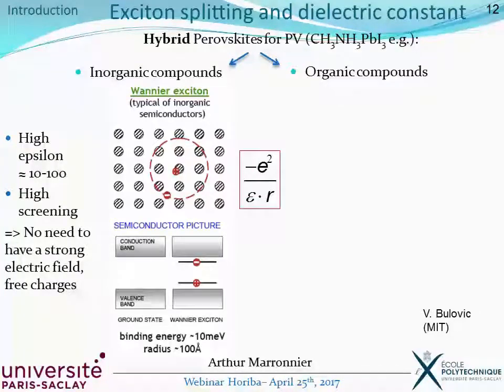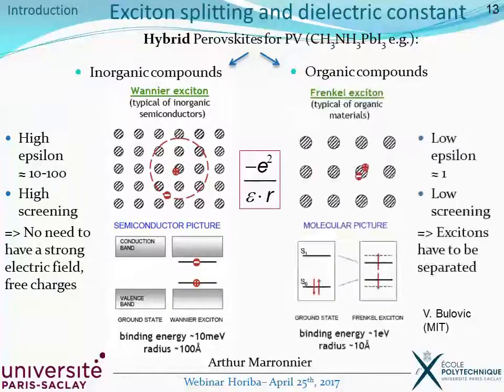And this is good news in general for photovoltaics, because it means that you don't need a strong electric field in order to extract your free carriers. And it's quite the opposite for organic compounds. They have Frenkel excitons, very tightly bound excitons, which are associated with a low value for epsilon, the dielectric constant, which is in general bad news for solar cells. You need a strong field in order to separate those excitons. So one of the first questions in my PhD was to understand where our hybrid perovskites fit in this picture.